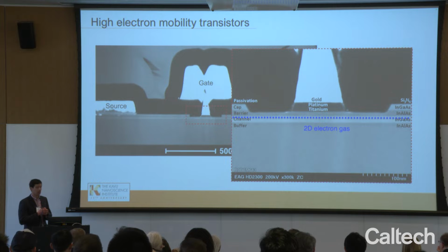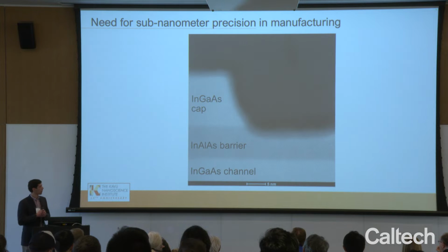Okay, now the challenge that we face, which is related to that issue with microelectronics, is that we can grow these materials with outstanding atomic perfection. You can see that in the image. But a thin film uniform over a wafer is not a device. What we need is some method of pattern transfer, where inevitably we have to etch or remove material from this device or from the film.